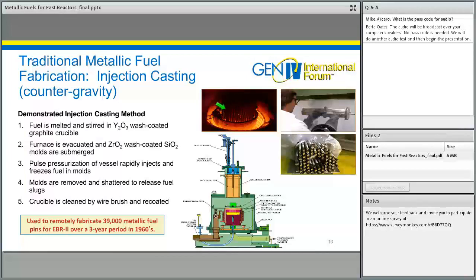initially under an inert atmosphere, but once it's achieved its molten temperature, it's melted with the proper superheat, the furnace chamber's evacuated down historically to a very hard vacuum. And then you bring in your molds from the top. These are quartz or zirconium or silicon oxide molds.